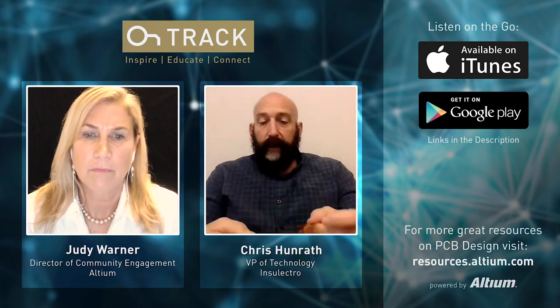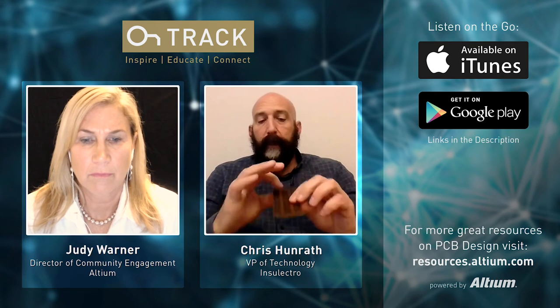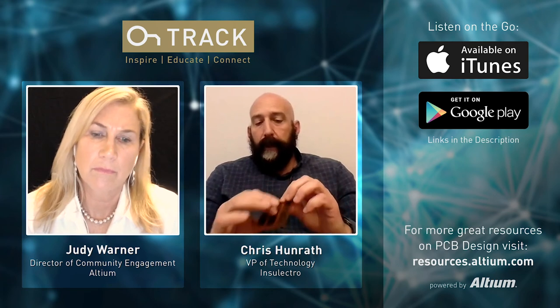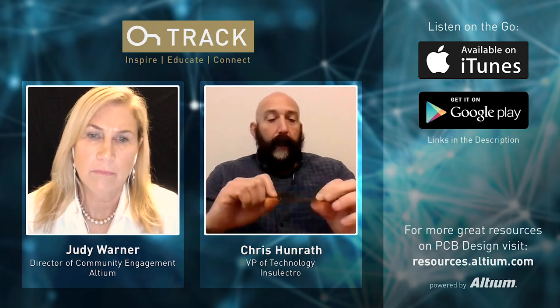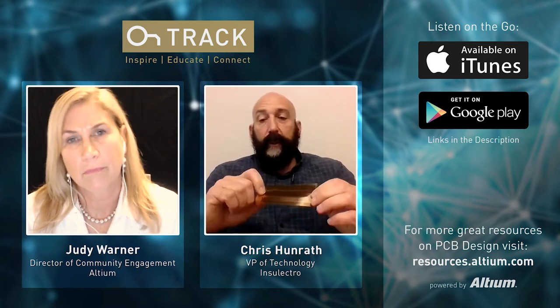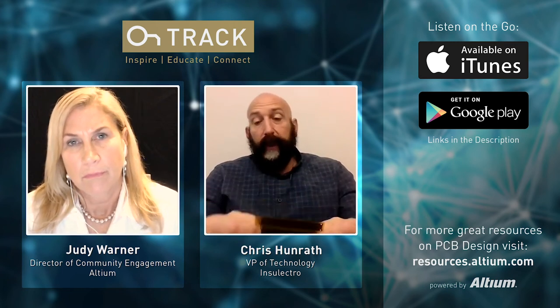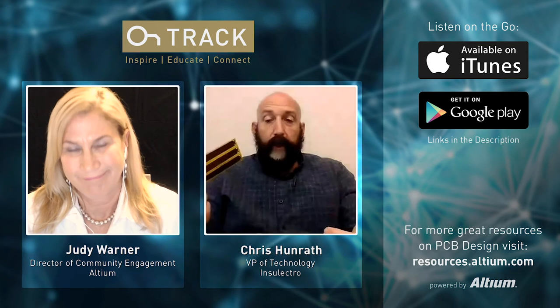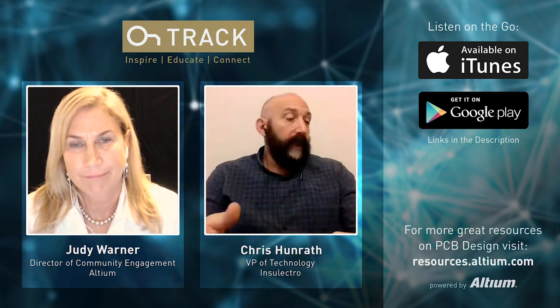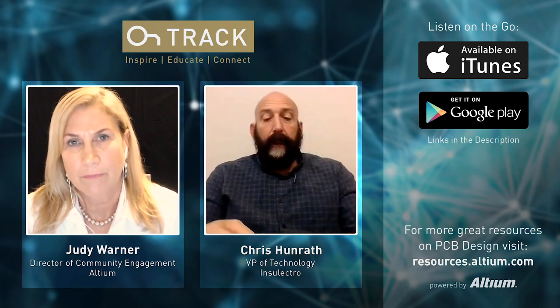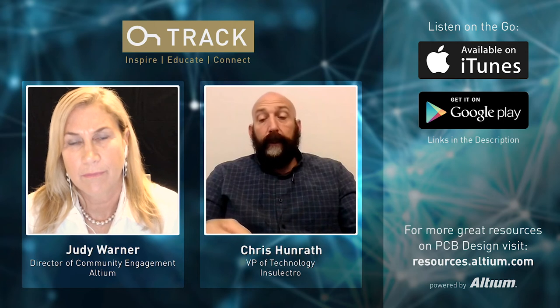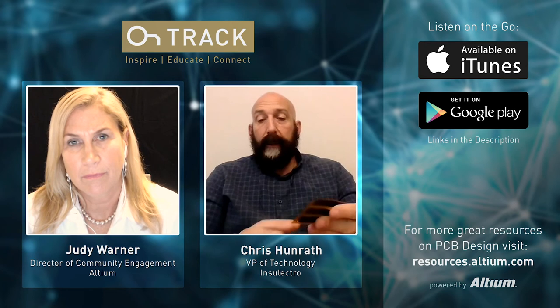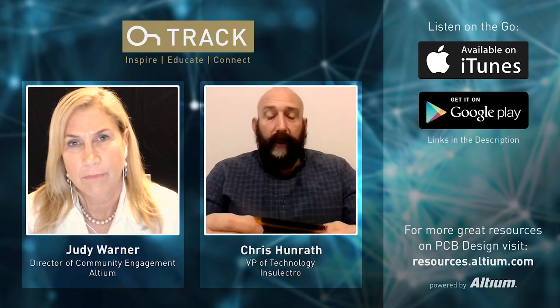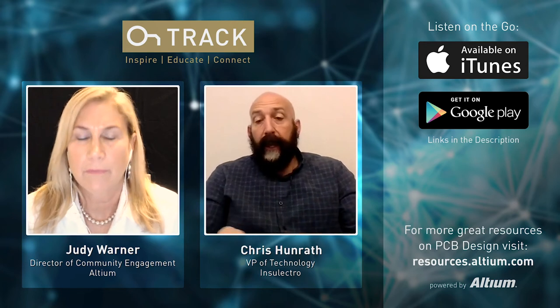Imagine if this were a strip line construction and you had copper on both sides, with your transmission line in the middle. One of the challenges with all PCBs, and especially with flex, is absorption of moisture, and then that moisture release during assembly causing delamination. One of the things you can do to mitigate that is to bake the parts. Well, if you have solid copper areas, baking does not work as well because the moisture has got to go around the copper. It can't go through it.